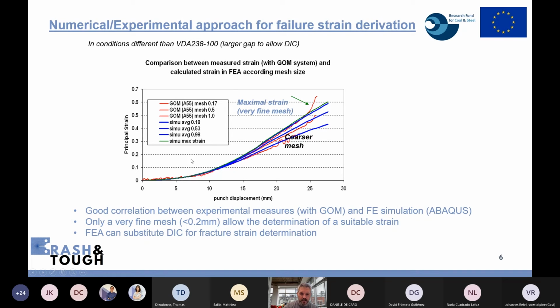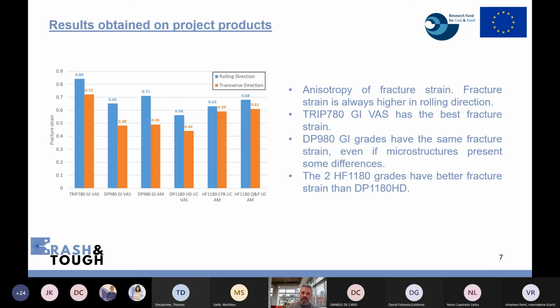We can see in this case that provided we are considering the same mesh size in the simulation, the blue curves, and the same grid size, the red curve, for DIC measurement, the simulation is in good agreement with the experimental test. Thus, it's possible for us to replace this purely experimental measurement by this hybrid approach: first the test, and then take the output of the test, the displacement at failure, as input for the numerical simulation, and then we will reach the fracture strain for all the products. That's it.